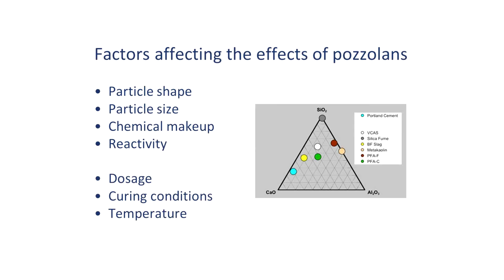They all have different chemistries. And so this little ternary diagram shows the various major chemical components of the different things. The blue dot is Portland cement. So where the different pozzolans fall on this triangular shaped chart illustrates the chemical makeup of these. Silica fume, which is a dark gray dot, is almost pure silica. It doesn't have any calcium in it, doesn't have any aluminum in it. Metakaolin doesn't have any calcium in it, but it has roughly equal parts silicon and aluminum in it. And blast furnace slag, the yellow dot, is closest to cement. It almost has no aluminum in it, but it's almost equal parts calcium and silicon. So that's how you read this diagram. I just showed it for illustration purposes. You don't have to care about any of that stuff.